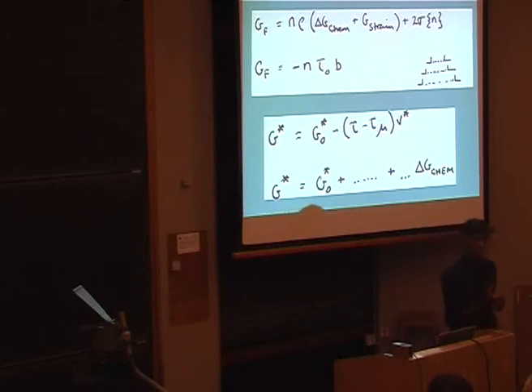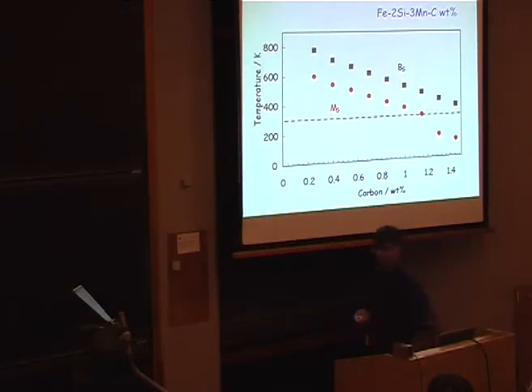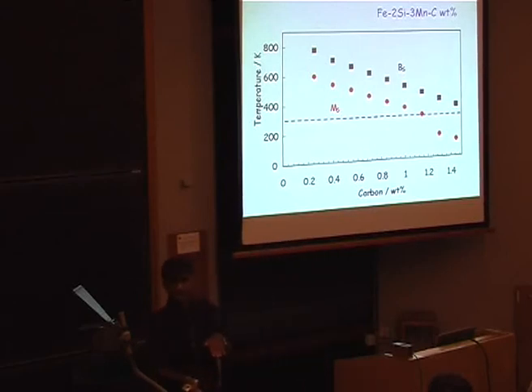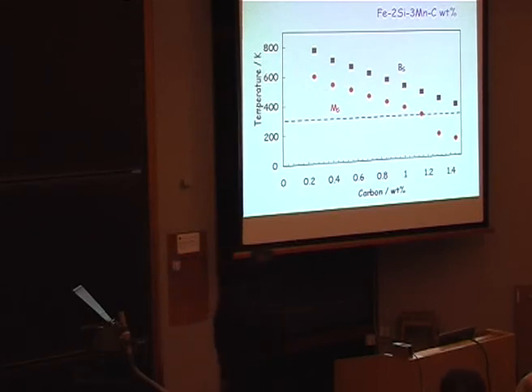I want to ask the question, what is the lowest temperature at which I can produce bainite? Well, here are some calculations, and the fortunate thing here is that I can keep the martensite start temperature and the bainite start temperature separate from each other. Because if they converged, then basically I couldn't go lower in temperature to produce bainite. Now, according to this, I could even produce bainite at room temperature. If I made an alloy with that concentration of carbon, I could produce bainite at room temperature.